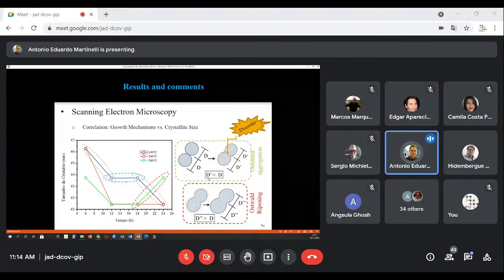So from these pictures, we can realize that the two mechanisms that take place here can be seen. Here are the different temperatures. Let's take, for example, 140 degrees C. As time goes on, we see oriented aggregation, as shown in the picture before. With oriented aggregation, because of this disordered area here, we see a slight reduction in the size of the crystallite, which is opposite from what we see at 180 degrees C, for instance, where we see particles growing by Ostwald ripening without the disordered area between them.